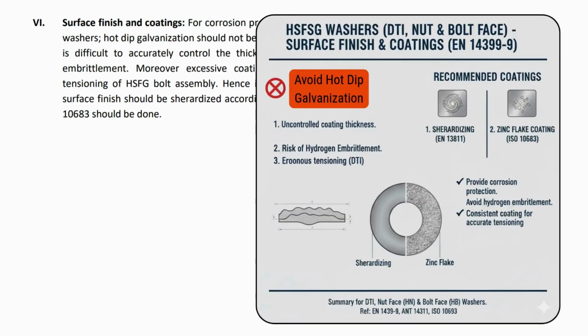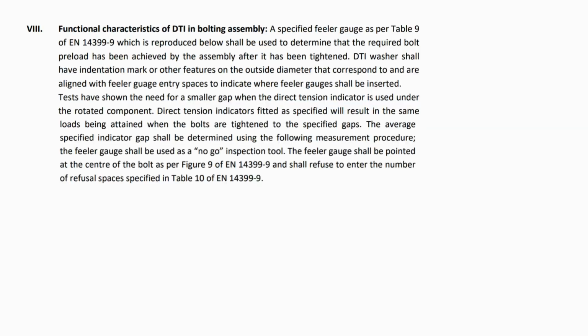For corrosion protection of DTI, nut face washers and bolt face washers, hot dip galvanization should not be done, because in case of hot dip galvanization, it is difficult to accurately control the thickness of coating as well as risk of hydrogen embrittlement. Moreover, excessive coating of DTI washers may lead to erroneous tensioning of HSFG bolt assembly. Hence, in DTI, nut face washer and bolt face washer, surface finish should be Sheradized according to EN 13811, or zinc flake coating as per ISO 10683 should be done.